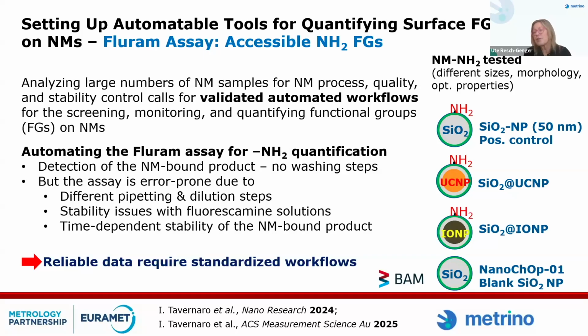We used it, for instance, for aminated silica particles, for upconversion particles bearing a silica shell with amine functionalities, or iron oxide particles with a silica shell and amine functionalities on the shell. The reason why we use it for these different nanoparticles is we simply wanted to see whether you have interferences caused by the optical properties of the respective nanomaterial. The nice thing is you can use it for a lot of different nanomaterials, and it can be automated, which we did. Because thereby you can screen a lot of different particles.